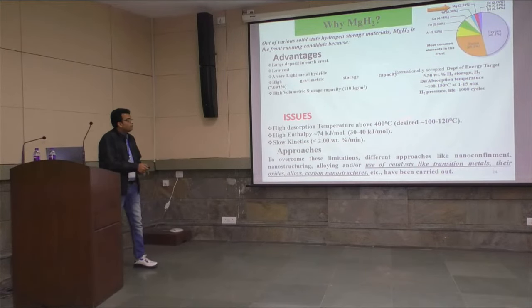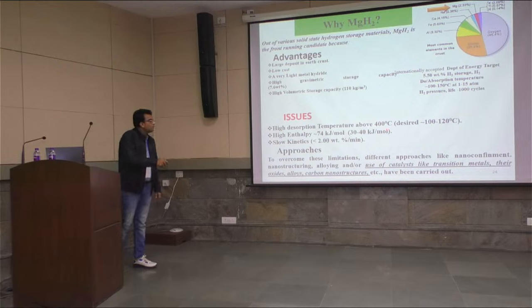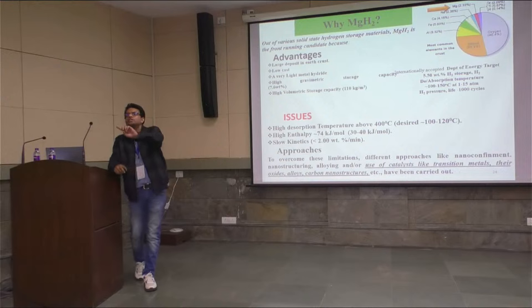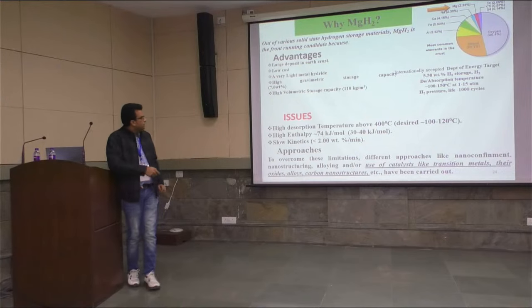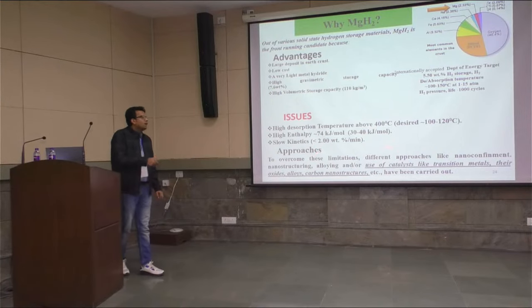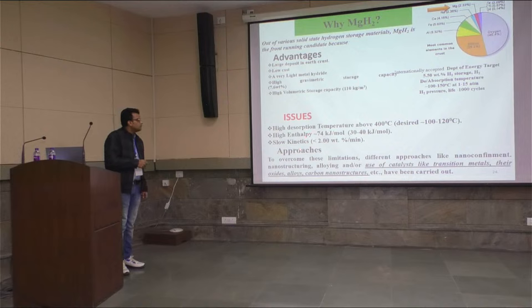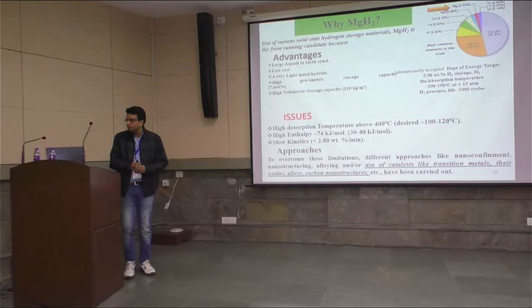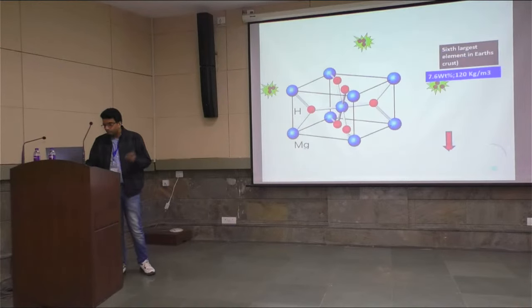So you have to reduce this temperature of dissociation of magnesium hydride to hydrogen from 400 degrees Celsius, and the reaction kinetics, magnesium hydride to magnesium, is also very slow. So these are the two aspects that you have to work upon, and for addressing these two aspects, we have used different catalysts and different dopants.